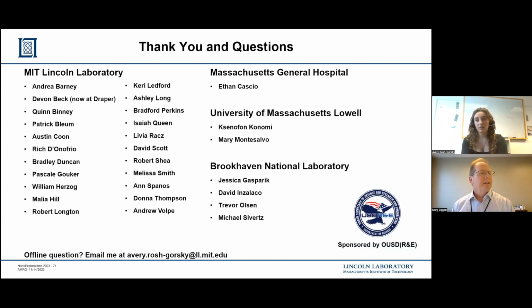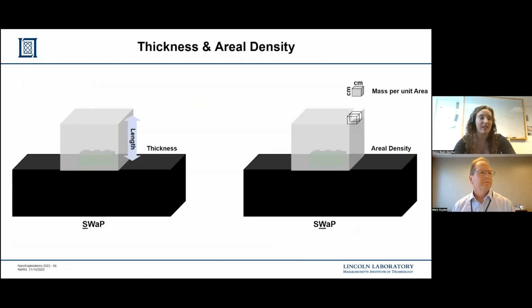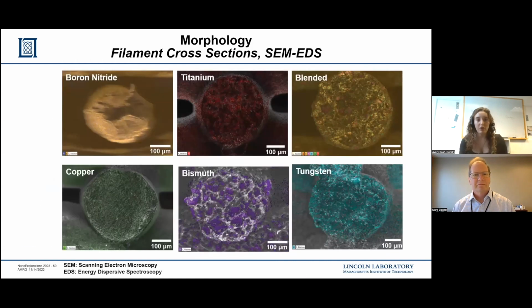Okay. The next question is, is nanoparticle size distribution an issue? So, I'll re-pull up the SEM images, because I think it shows it really well. As you can see, with everything but the bismuth, the nanoparticles are distributed really well throughout the filament. It's when the nanoparticles are too big that they are agglomerated. That causes a lot of difficulties with printing, because it tends to clog the nozzle tip. And just a side note on that, a lot of commercial nanoparticles, when you buy them, are not the size that they say. So we usually have to run them through SEM to make sure that they will behave the way we want them to in the filaments.